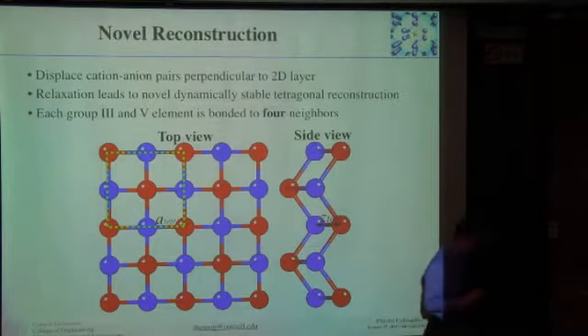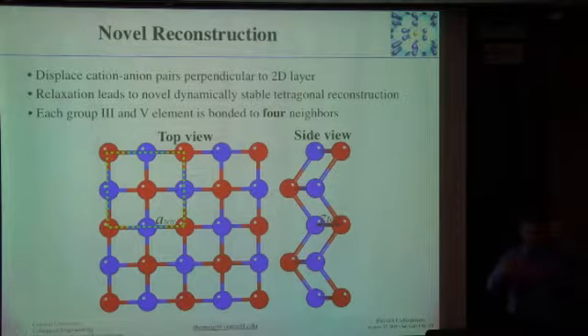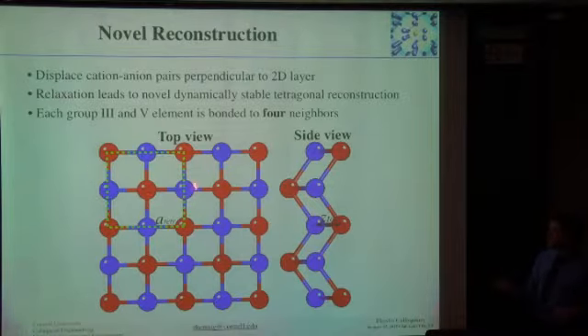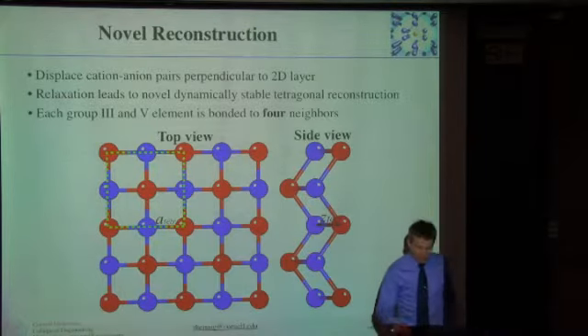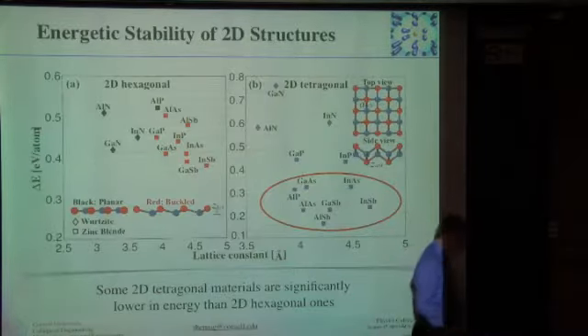But one interesting thing we find is some of these structures are mechanically unstable, just like what you pointed out, shown in the phonon spectrum. And then when you relax them and you come up with alternative ways of making those structures, we come up with a version which isn't hexagonal, which is tetragonal, where you have, this is a top view. So instead of hexagons, you get squares, and the side view is they buckled. So this is an image of aluminum phosphide, for example. These are the aluminum atoms, planar, 4-fold coordinated, phosphorus, 4-fold coordinated above and below. So this is a new structure form, and it turns out that some of those have significantly lower formation energies.